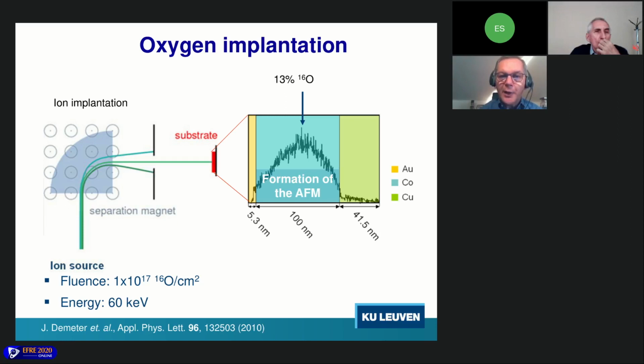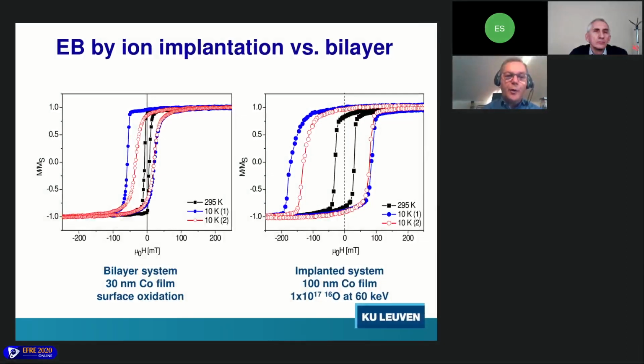You can see at the maximum, which is more or less in the middle of the layer, which is 100 nanometer thick, you have about 13% of oxygen. We did this with a fluence of 10 to the 17th ions per square centimeter and an energy of 60 kiloelectron volt. Now let's take a look.